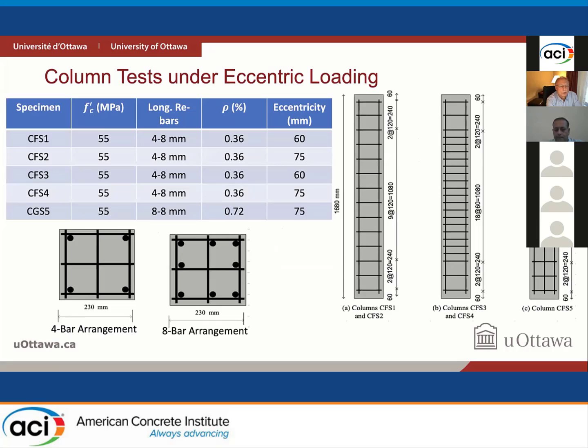We tested a total of 5 columns, and the objective of these tests, they were approximately 1.7 meter in height, and they were tested under universal testing machine. The objective was to see behavior of these bars in compression under different levels of eccentricity, and also to see if we can use the strain compatibility analysis that we always use for sectional analysis for steel reinforced concrete columns, and see if the same analytical techniques that we use for steel reinforced concrete columns are applicable to those columns